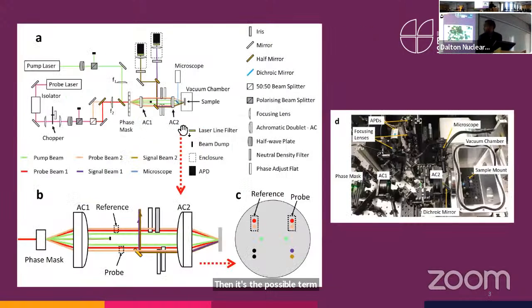And this is a schematic of how the setup works. I won't go through this. Basically, these are your excitation lasers, and this is your probing laser. And then we have a sample, in a vacuum for the thermal diffusivity. And we use silicon photodiodes to measure the intensity of the signal beams. And this is a snapshot of just this bit of the setup. And we also put in a microscope so we can look at what point on our sample we're actually measuring.